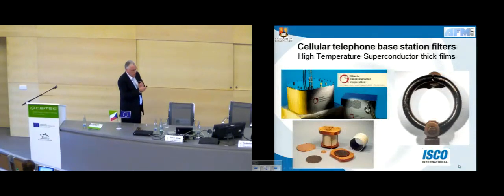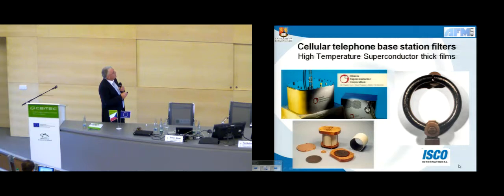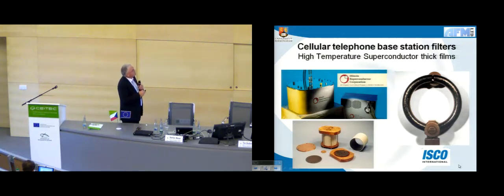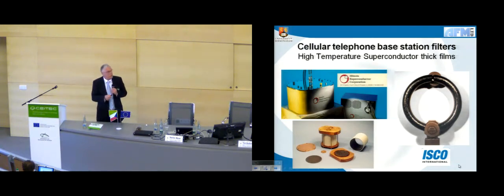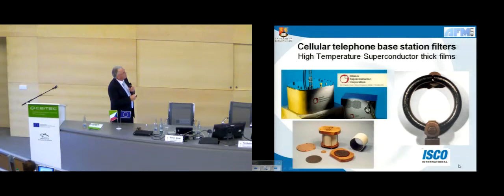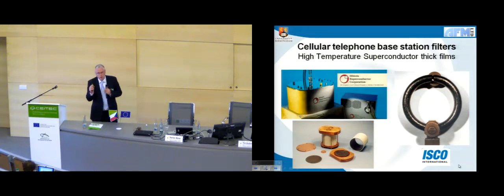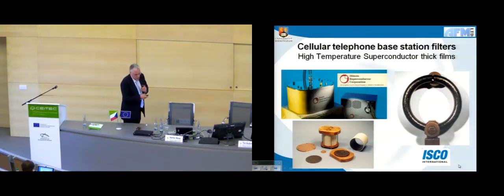You can see here some of the challenges that we've had. The actual devices are usually three-dimensional devices, either these cavity-type structures or perhaps even this ring-type structure. There is a gap in the ring that you probably can't see very well. These have a ceramic substrate of some sort, in this case zirconia, zirconium dioxide. But the key property is the properties of this black superconductor coating on the surface. We've had to develop techniques to be able to coat these films. These films are probably around 40 or 50 microns in thickness. As I say, the key is in their properties. And this is technology that we developed in the UK and actually transferred to the USA.